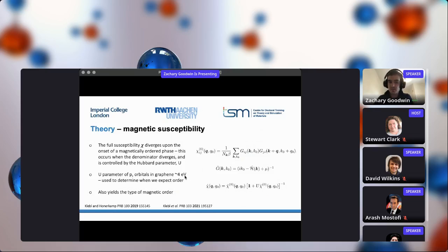In graphene, it's known that the on-site Hubbard parameter of the pz orbitals is about 4 electron volts. So we can use this as a criterion for deciding when we expect to observe magnetic order and when we do not. If our critical on-site Hubbard parameter is larger than 4 electron volts, we don't expect to observe magnetic order, but if it's lower than 4 electron volts, we do expect to observe magnetic order. And it also yields the type of magnetic order that occurs.